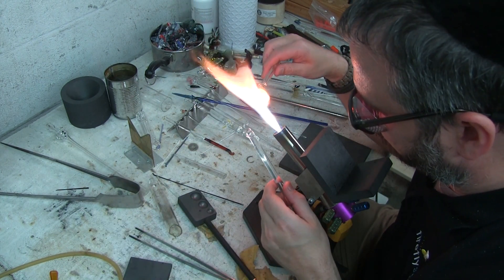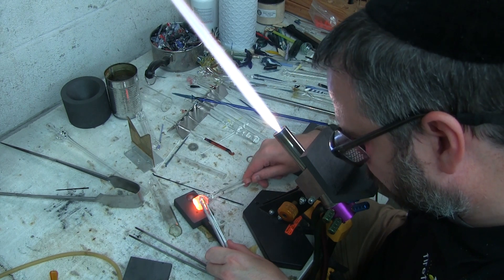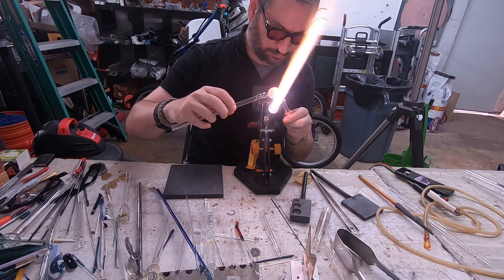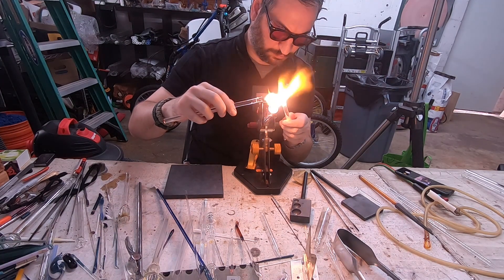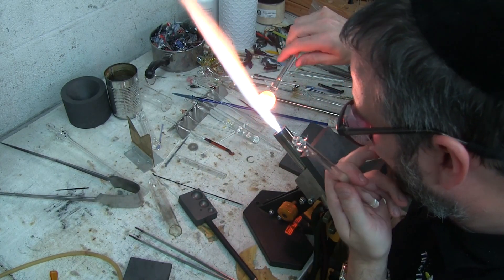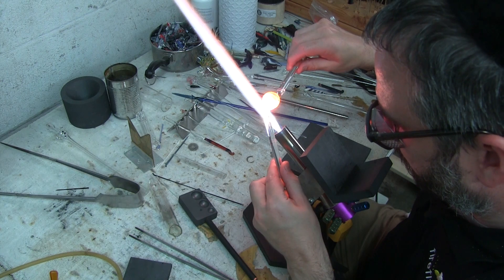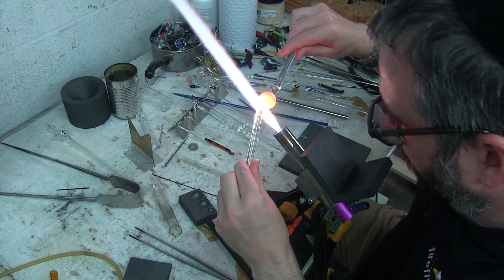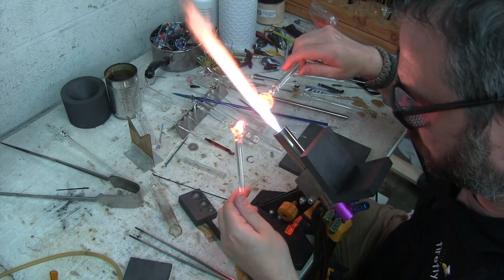Now I do have a little bit of extra glass that I'm going to peel off. Not wanting to trap any air bubbles as we do this. We're going to smush the glass down and peel off anything extra. Keep the glass you want to peel off in the flame and just touch your rod to it and it should come right off. Make sure you cut your glass in the flame and not outside to avoid making really thin stringers. Always cut your glass in the flame — you don't want those really fine hair glass stringers around. You can get splinters and they snap easily and they're really hard to see. So I always vacuum off my work area to get rid of all those tiny little stringers.